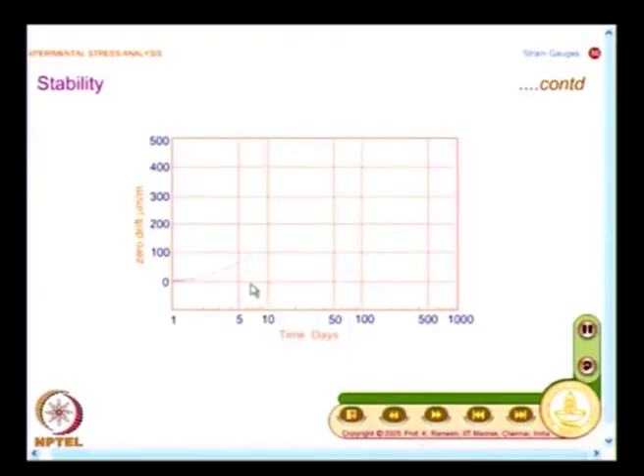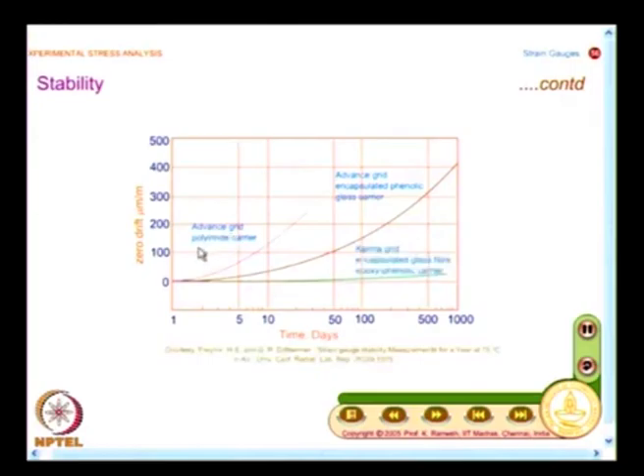I have a graph which shows time versus zero shift. Time is plotted in a log scale. I have 10 days, 100 days and 1000 days. And I have 3 graphs. I have one graph for strain gauge alloy advanced grid and polyimide carrier, and the second graph, the grid material is the same, it is again advanced grid encapsulated with a phenolic glass carrier. The carrier is made different. You have the encapsulation and you have the phenolic glass carrier.